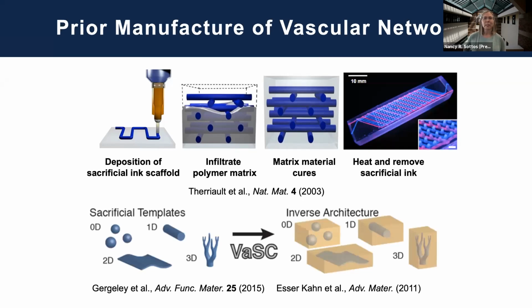And we quickly realized that it was limited, especially towards aerospace grade composites, that the sacrificial inks just wouldn't survive in a composite and hold their structure. Then we moved on to this process we lovingly called VASC, which is vaporization of sacrificial components, where we did a lot of work on developing sacrificial polymer templates that would be embedded in the polymer that can survive the cure cycle and then go through a second heat cycle to vaporize the material and leave the architecture that you want in forms of empty channels or networks.